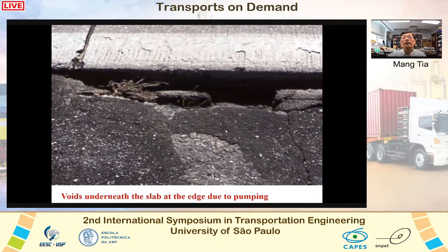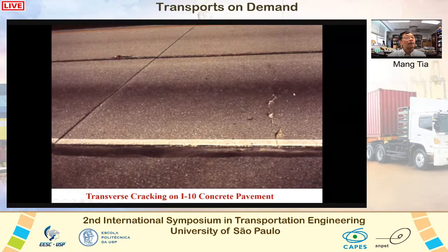Pumping was due to water which is trapped under the concrete slab, and is pumped out of the edge of the concrete slab when heavy vehicles go over the slab. Pumping causes erosion of the subbase materials underneath the slab and creates voids underneath the slab, as you can see from this picture. Due to lack of support underneath the concrete slabs, cracking occurred. This is an example of cracking which was observed on that pavement.